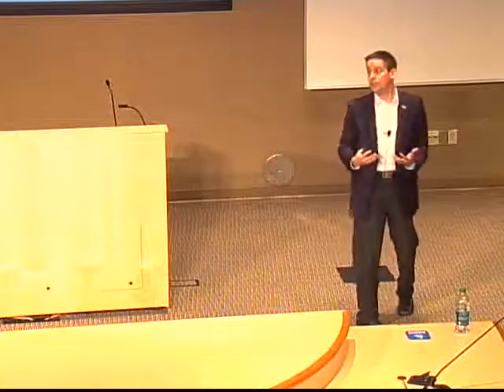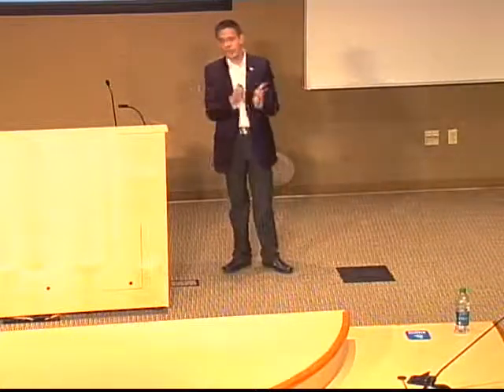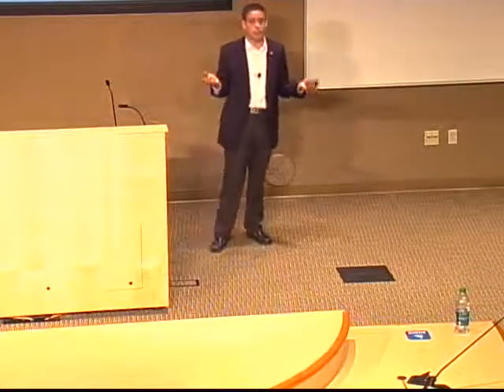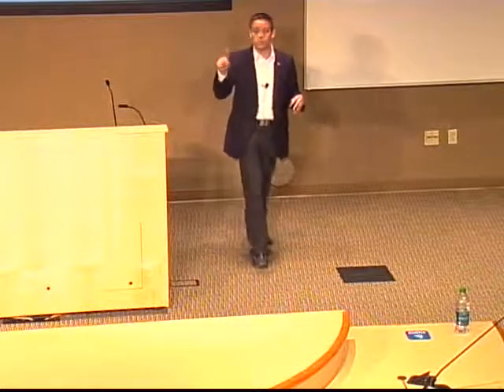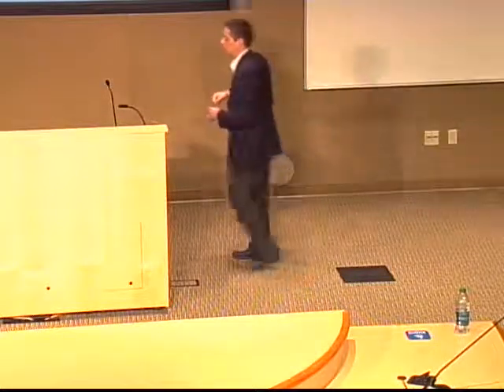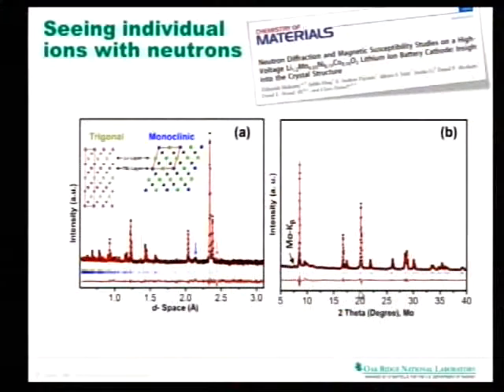Typically, the way we can very well look at phases of materials is we use X-ray diffraction. We look at the crystal structure. We can look at average distances of atoms and ions in there and get a pretty good idea. In this case, there's no way for you to see the changes going on inside the lithium ion because it's so light and the changes it's doing are not detectable with your X-rays. So that's where Oak Ridge's neutrons are coming in.